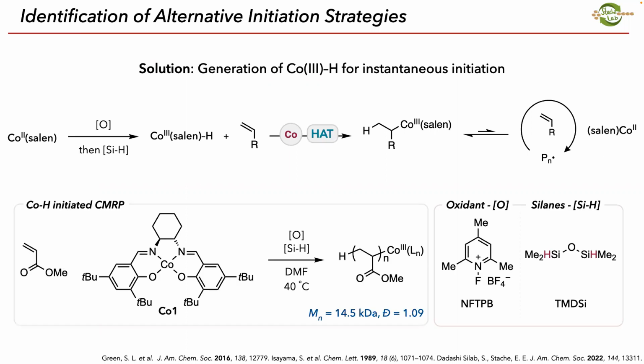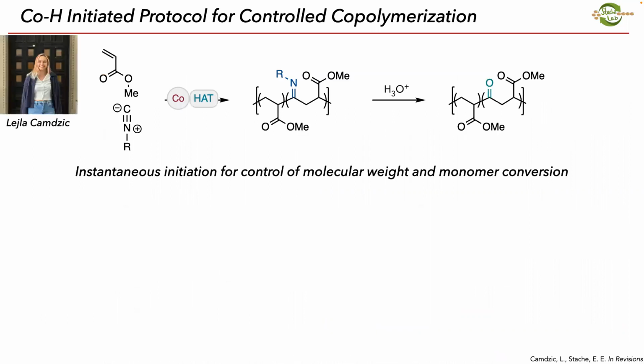So now we can run the polymerization. And so using this cobalt complex, methyl acrylates, this oxidant and silane, which aren't really too important, he now gets a very well-controlled polymerization. So the molecular weight that we programmed in is exactly what we see. And the dispersities now are less than 1.1. So this shows us that the chains are very uniform in length, and we have control over the polymerization. Now there's a lot more interesting mechanistic nuance to this, but I really want to focus on sustainable polymer chemistry now. So I'm going to show how we use this then in copolymerizing isocyanides with methyl acrylate.